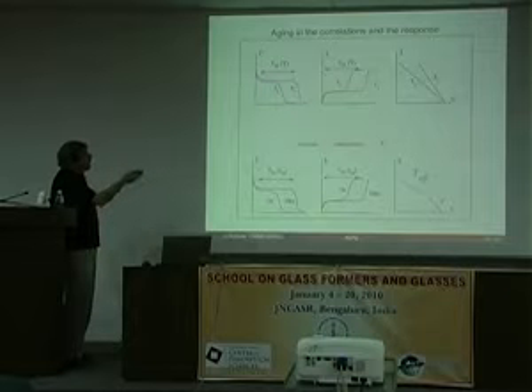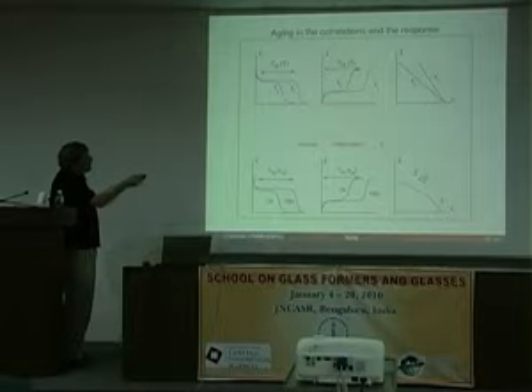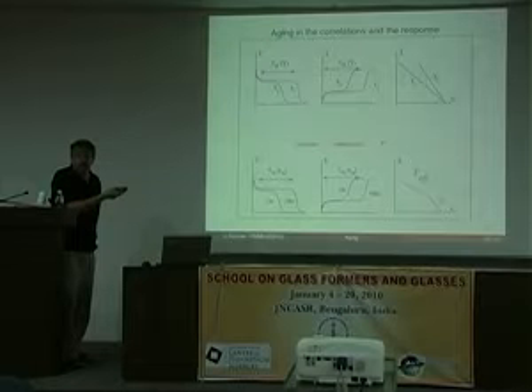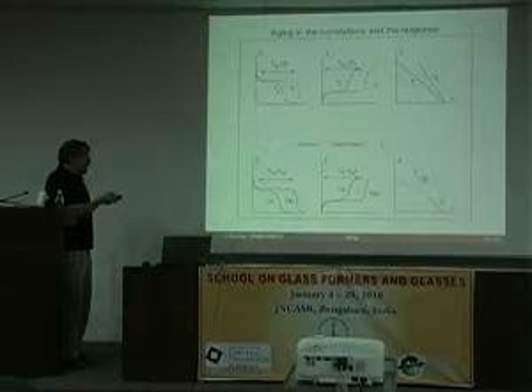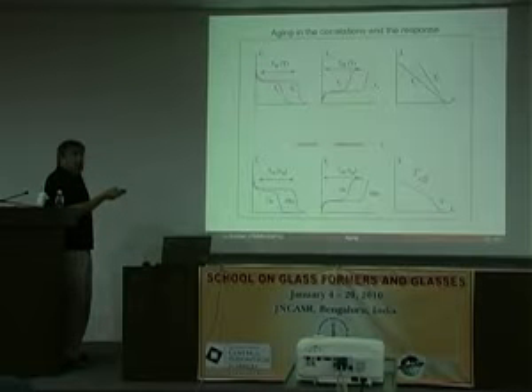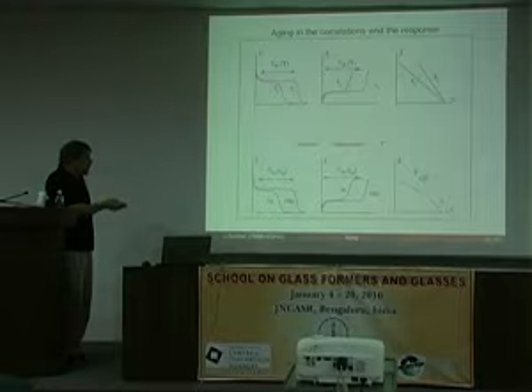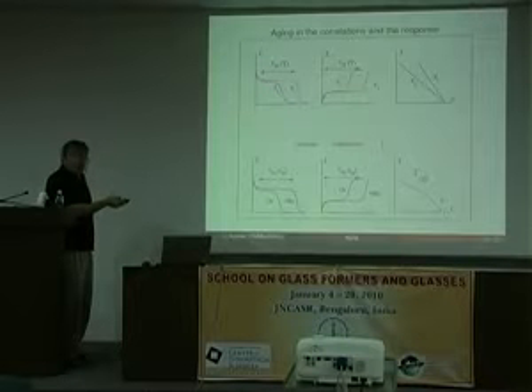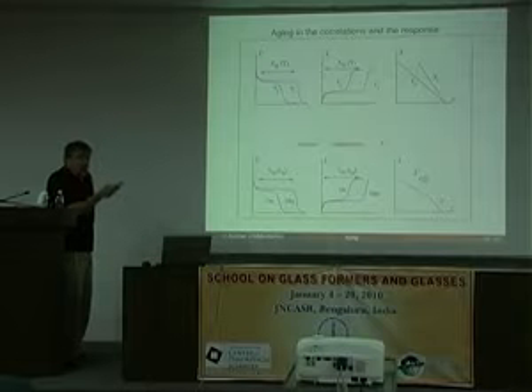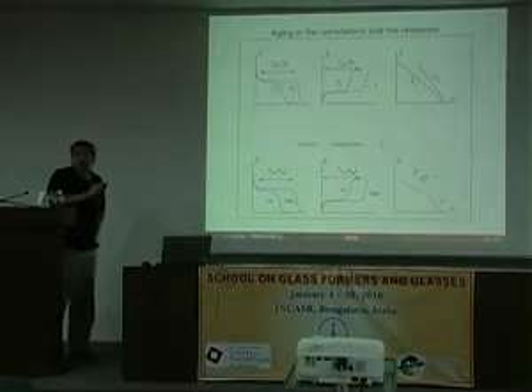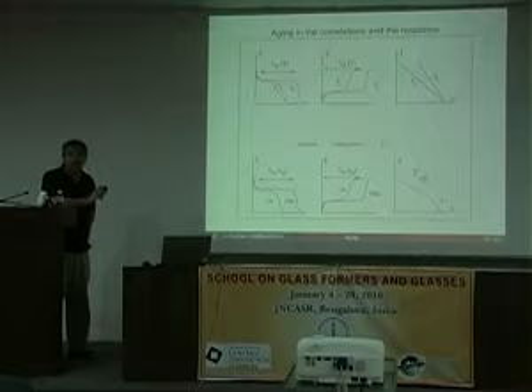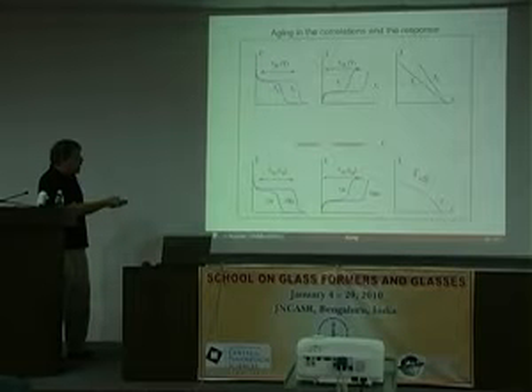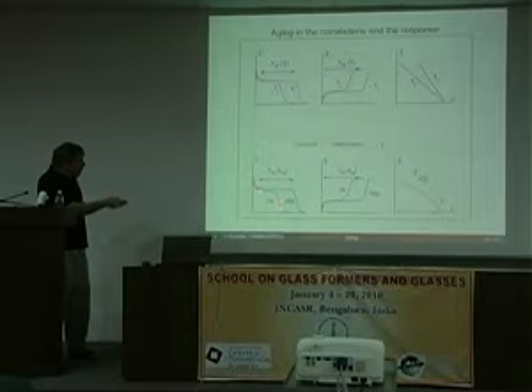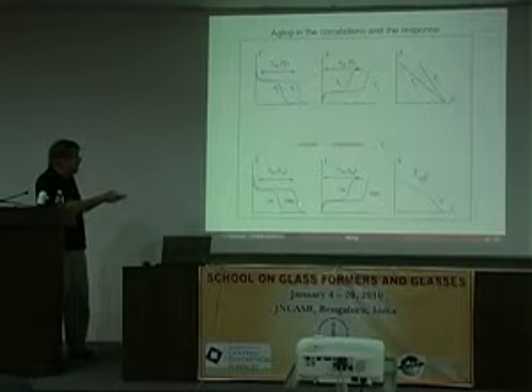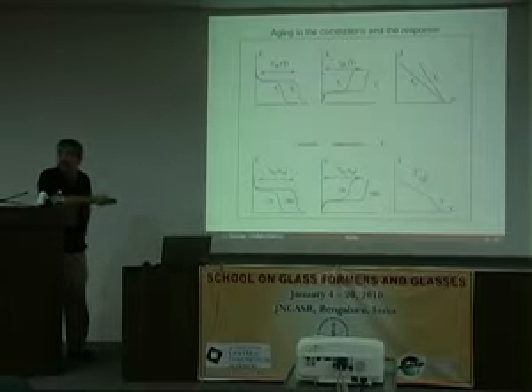In any case, if you make a plot of C versus chi, you get straight lines at the temperatures at which you are in equilibrium. Now, I told you that below the transition temperature, you could solve exactly the system for the correlation and the response. You didn't assume fluctuation dissipation. There's no reason there should be fluctuation dissipation because this is an equilibrium theorem. But you are allowed to do a parametric plot: the 1-hour curve of correlation against the 1-hour curve of response, the 10-hour curve of correlation against the 10-hour curve of response.